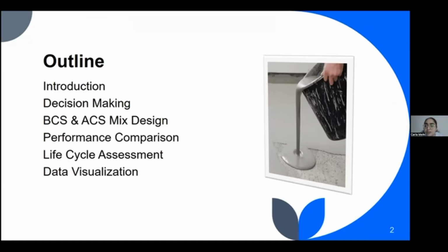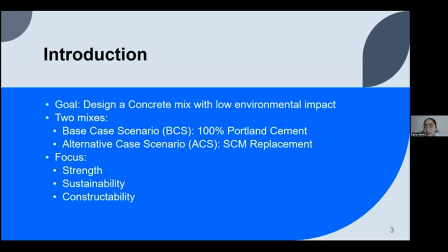Our goal was to design a concrete mix that not only meets performance standards but also significantly reduces environmental impact. We created two mixes, a base case scenario using only Portland cement and an alternative case scenario where we replaced a percentage of the cement with supplementary cementitious materials. By doing this, we reduced CO2 emissions, improved the durability, and kept the same overall material volume. Throughout the project, we focused on sustainability without compromising strength or constructability, and we are proud of the balance that we have achieved.